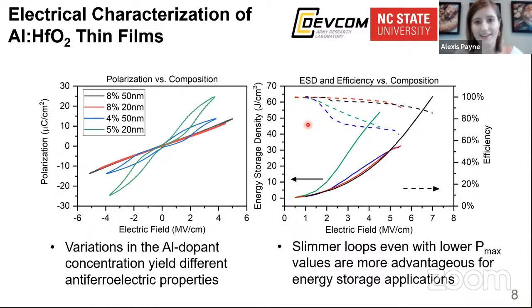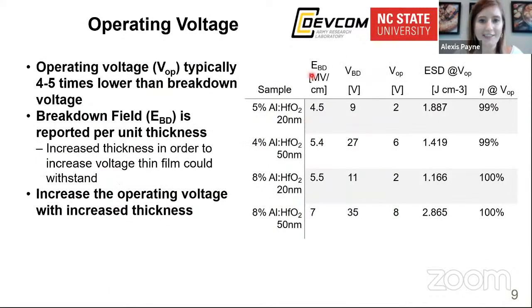Now, this is one way of looking at these thin films, but in reality, for thinking about using them in a device, you have to consider the operating voltage. The operating voltage is typically 4 to 5 times lower than the breakdown voltage. So as much as we can look at them at the extremes, you would never run your device at those extremes, as you would experience breakdown rapidly. So you always back down from that extreme value. And that's why the operating voltage is significantly lower than the breakdown voltage.